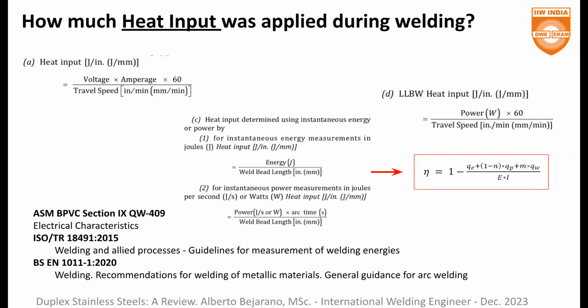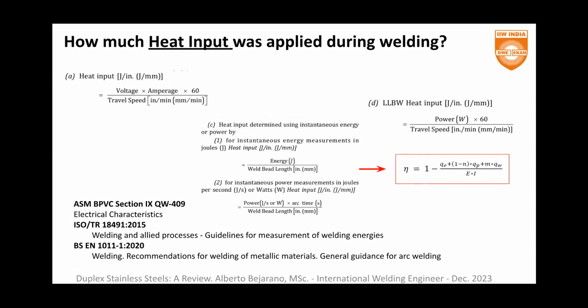We need a cooling rate enough to produce enough austenite, because remember that these alloys solidify 100% ferritic, okay? And not too much, in order to prevent the segregation of the deleterious phases. So, have this in mind, who defines the cooling rate?